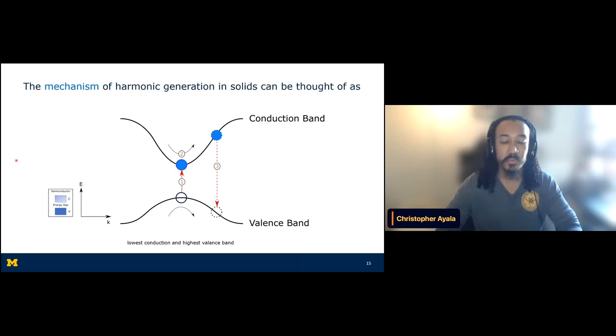The main difference between a gas phase high harmonic and a solid harmonic is not quite too different. You see here that the tunneling and ionization is represented by step 1, with the electron being pulled into the conduction band and leaving a hole pair. In step 2, you have the propagation of your electron, and in step 3, you have the recombination back into the valence band. In the case of harmonics in solids, there are actually 2 generations of harmonics that are known.